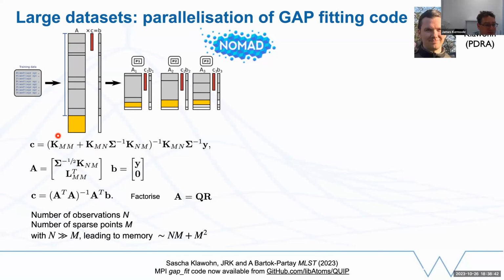So the original way this was done was with a giant matrix A and a giant vector of observations B that contains all our energies and forces, and then we want to get out these coefficients C here. And what Sascha proposed is splitting that up into a series of independent matrices that can be distributed across a large machine, and then we can do that construction of these matrices and the linear solve and the solution of the least squares problem in parallel.